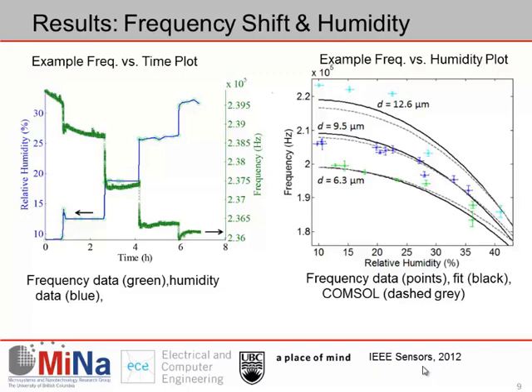Number one, the frequency is falling. This is because there's likely an increase in mass. Also, there could be potentially a decrease in tension or a decrease in stiffness, but we'll talk about that a bit later. Also, the resonant frequency is quite low. That's around 200 kilohertz. And I say quite low because it's quite low for a resonator of this size. And the reason for that is because we have such a low Young's modulus.